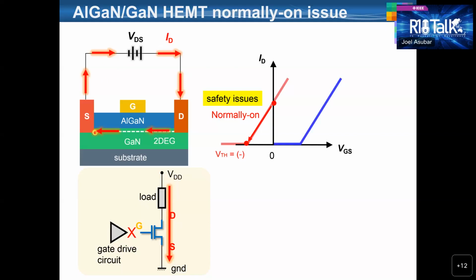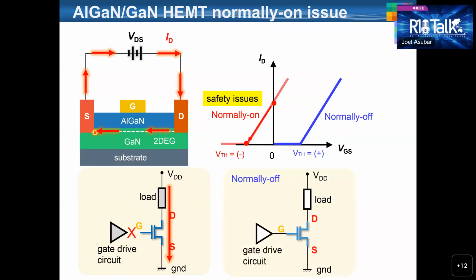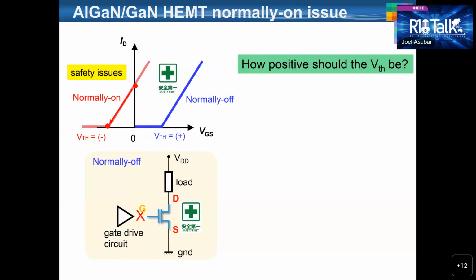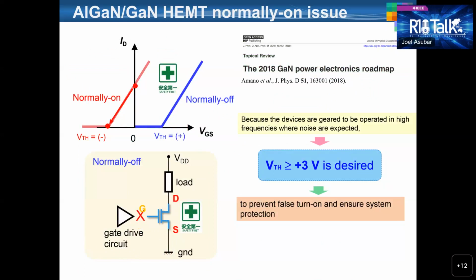And normally off devices with positive VTH are more desirable. For normally off devices, if the gate drive circuit encounters some problem causing disconnection from the gate, current remains 0, making normally off devices desirable from a fail-safe point of view. Now the question is, how positive should the threshold voltage be? Because the devices are geared to be operated at high frequencies where noise in the form of unwanted oscillations and ringing are expected, a threshold voltage of at least positive 3 volts is desirable to prevent false turn on and ensure system protection.